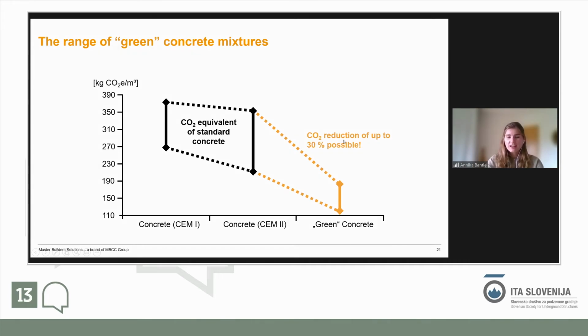But where we really have the leverage is when we are using CO2 optimized concretes, or also called green concretes, sometimes called like that. And we have a CO2 reduction possibility of up to 30%, to really push the embodied carbon of a cubic meter quite below 200 kg.